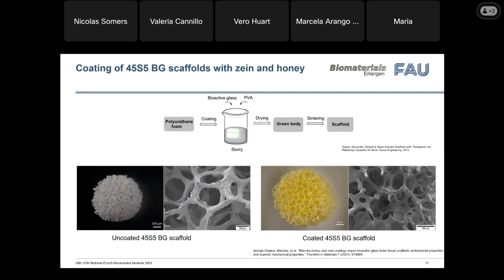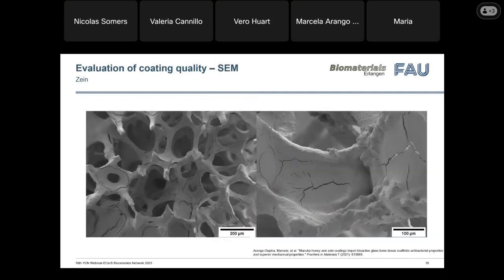So here we can observe the glass scaffolds, and after the coating, we have this yellow color, which is given by the zein. Here we can have a closer look at the coated scaffold. We observe that we still have a porous structure, but with a few blockages, so pores that are blocked. But in general, we can see a good coverage and also a smooth surface. And then on some pores, we can see some cracks from the zein.